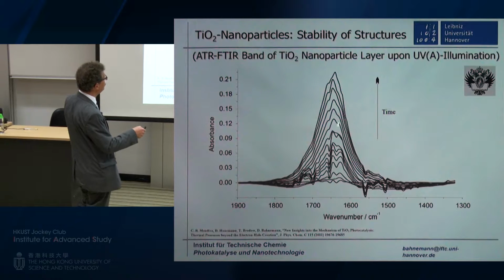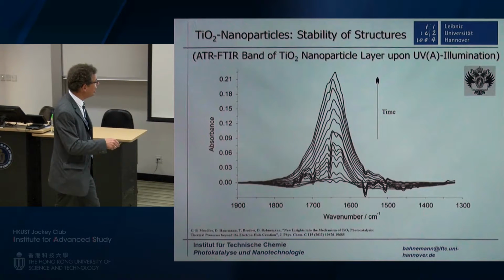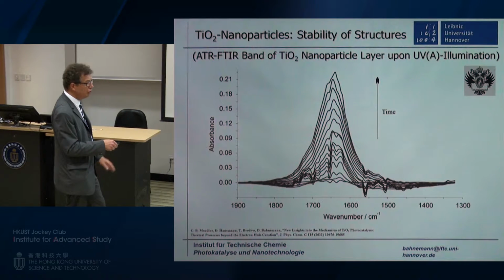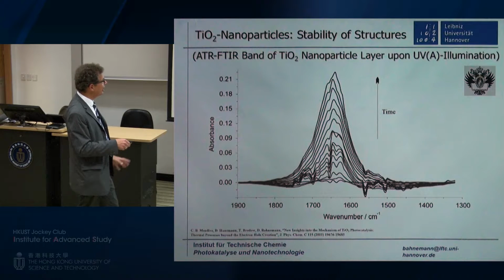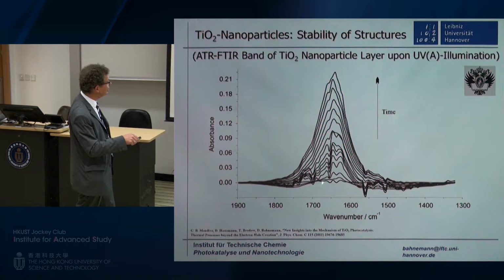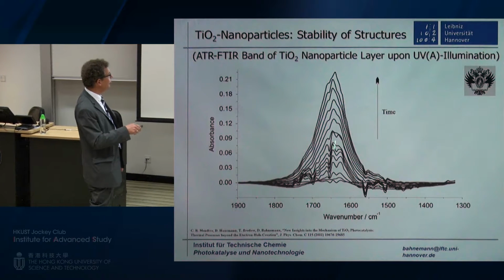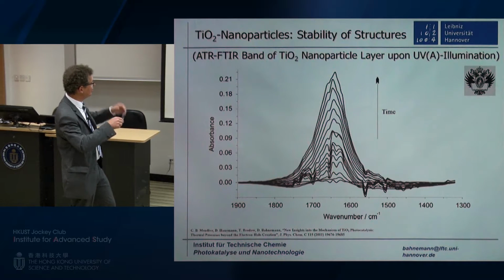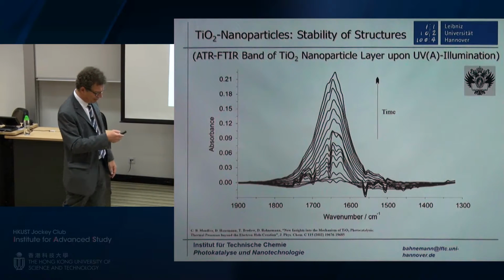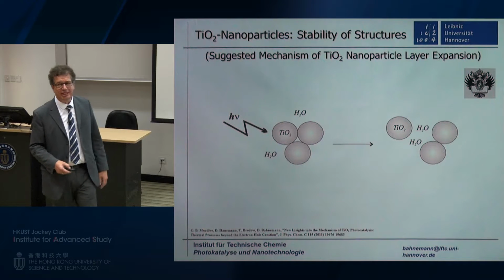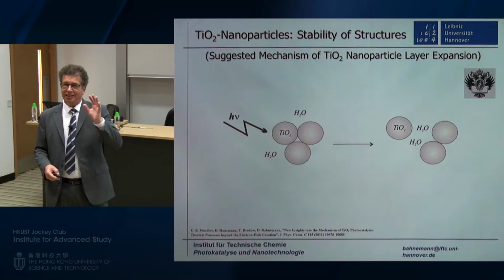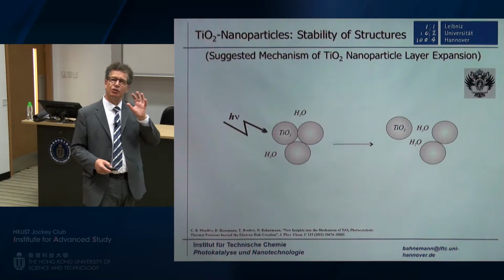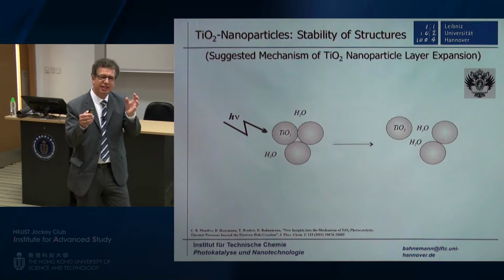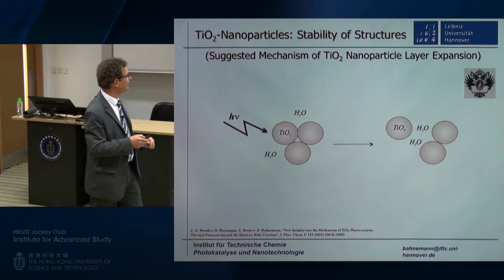We see with illumination time, it's UVA illumination around 360 nanometer light, which is absorbed by the TiO2, not by the water. So the water is not excited, the TiO2 is excited, and you see that these bands around 1600 and some wave numbers, they are increasing, and it looks quite interesting what we find here. So how can we explain what's happening? And one explanation takes into account this pre-existing network of nanoparticles.